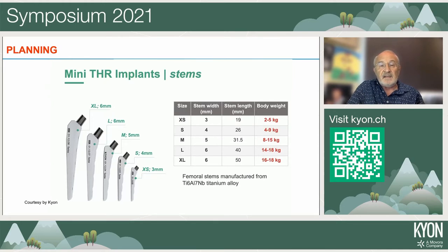Also, we have a guideline for the body weight of the dog, so the most indicated size of the implants. For instance, the 3 millimeter stem is suitable for dogs or cats from 2 to 5 kilograms, and the 4 millimeter stem is suitable for 4 to 9 kilograms, and so on. That is a useful guideline also to provide a good guarantee to the owners for the tolerability of the implants according to the body weight.